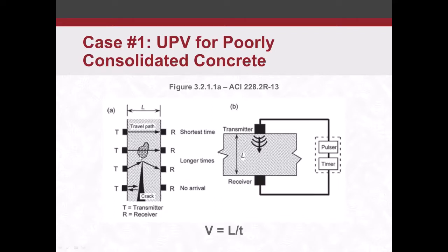As things internal in the concrete are changing, you've got maybe some soil intrusions if we're using the cross-hole sonic logging method, or maybe some voids or poorly consolidated concrete or some other sort of anomaly in the concrete, that's going to slow down your wave speed. Maybe there's a crack or lots of voids, and the wave is not going to transmit through air, so it kind of goes around the voids. Obviously that's a longer travel length, and it's going to take longer to travel before it's received, so it's going to give us a lower wave velocity. Or maybe in some cases the crack is so bad that we just don't receive any signal at all on the other side.